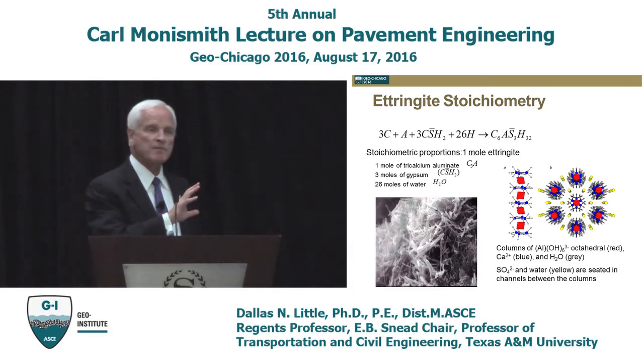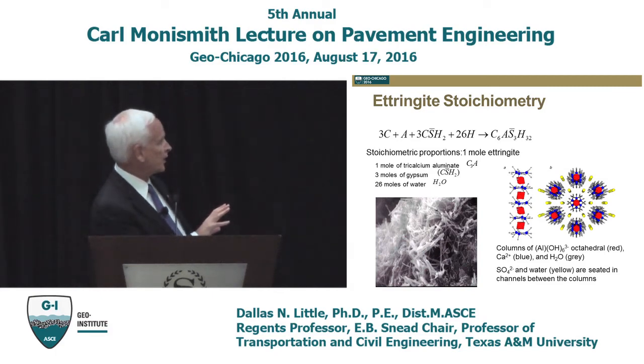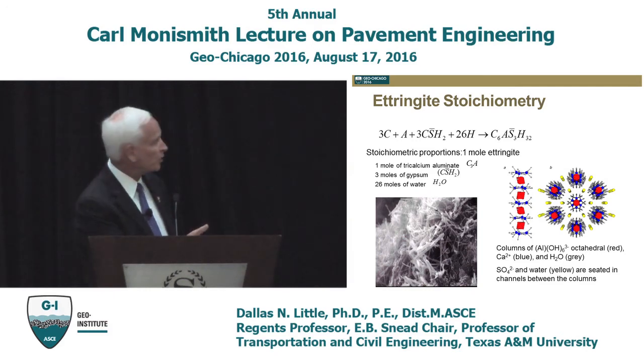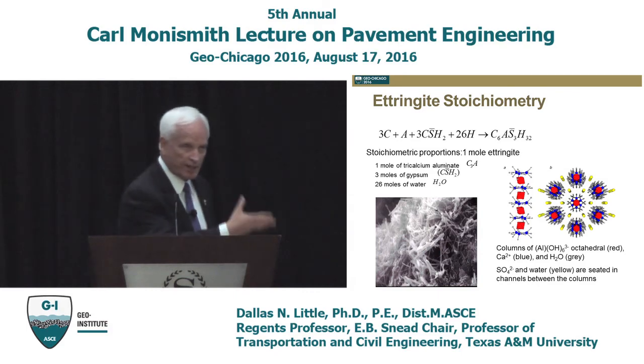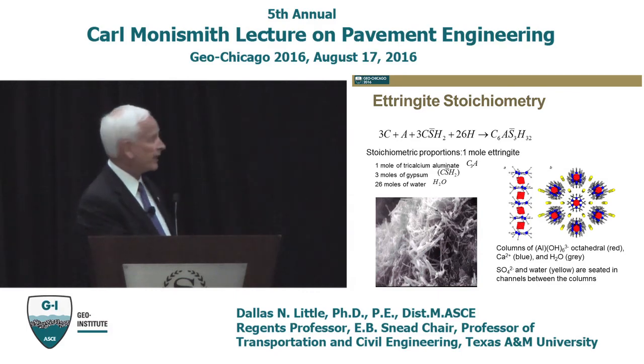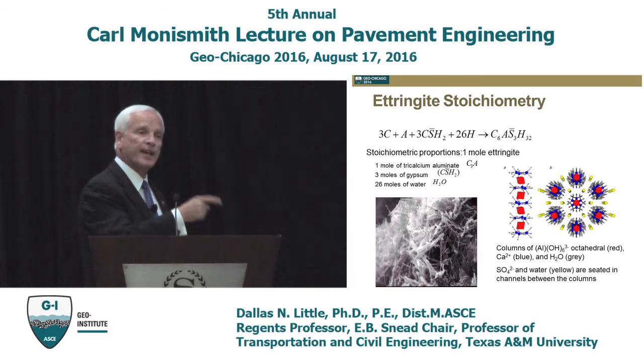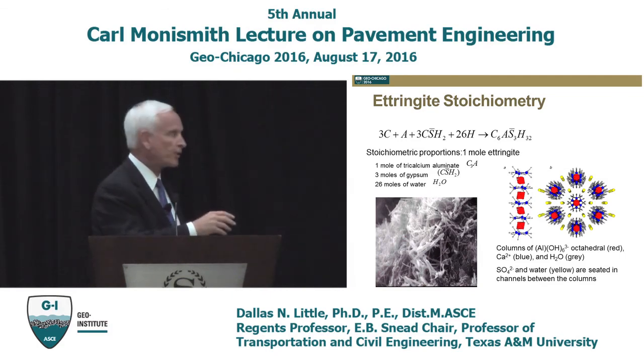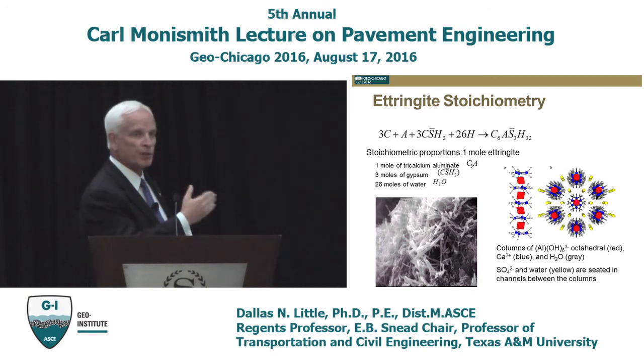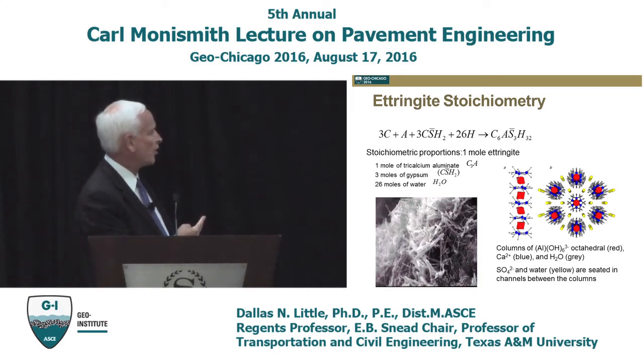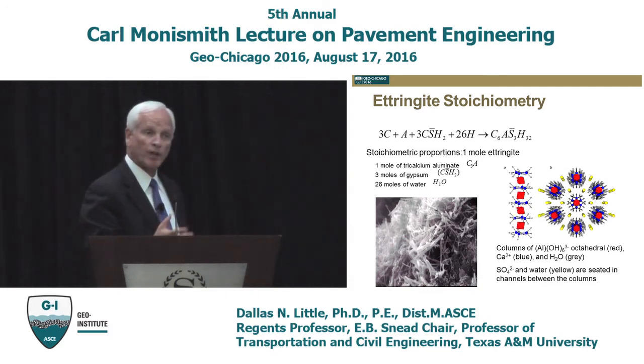And if you look at the molar volumes of those components, to form 1 mole of ettringite, it takes 1 mole of C3A. C is a shorthand for calcium oxide, A is a shorthand for aluminate. So C3A, 1 mole, it takes 3 moles of gypsum, C once again for lime, S bar for sulfate, and H for water. And it takes 26 moles of water, a whole lot of water.